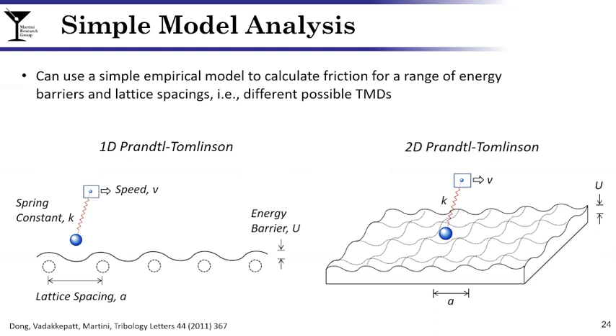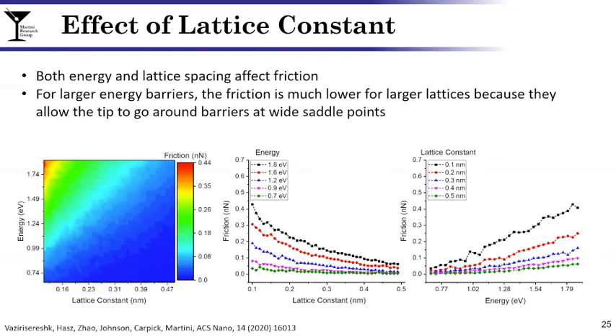So let's look at the Prandtl-Tomlinson results. On the far left, you're looking at a friction map where we have energy and a lattice constant, and the friction magnitude is reflected by the color. On the far right, we see friction as a function of energy barrier. So as one might expect, the higher the barriers, the higher the friction.